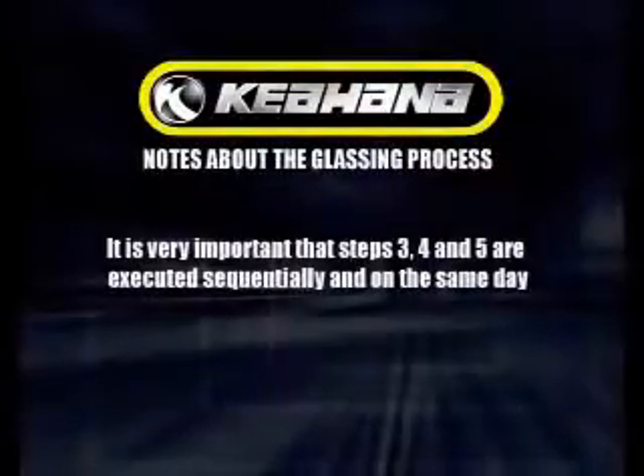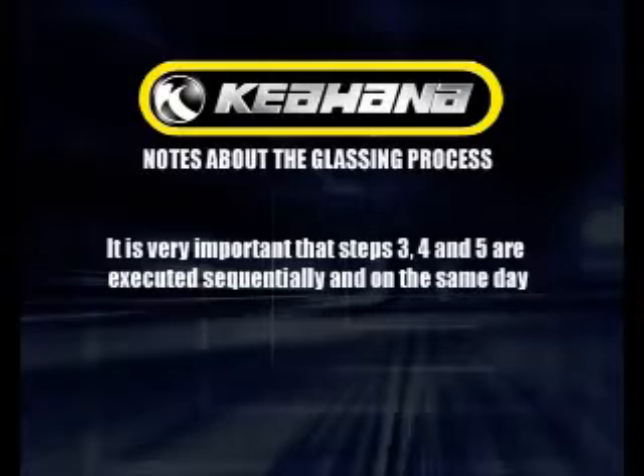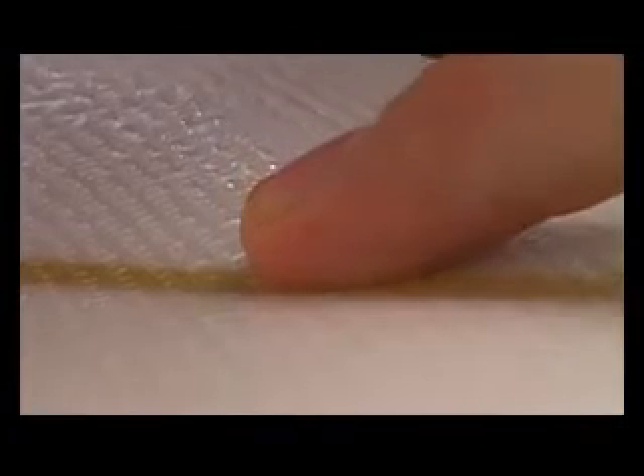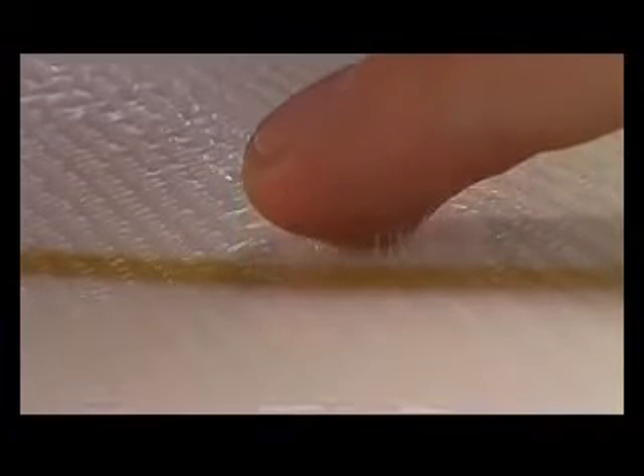It is very important that Step 3, glassing bottom, Step 4, glassing deck, and Step 5, hot coat deck, are executed sequentially and on the same day. To test when the glassing is getting to its gel point, touch the glassing with a clean finger. If the resin has gelled enough, there will be a fingerprint left on the glass. Do not allow the resin on the bottom to dry before you glass the deck.